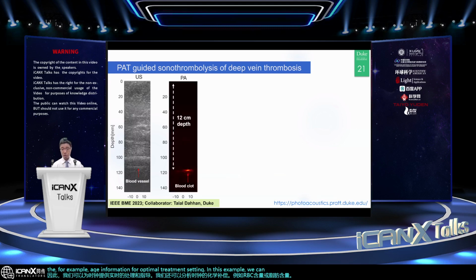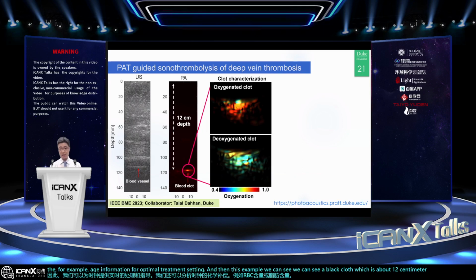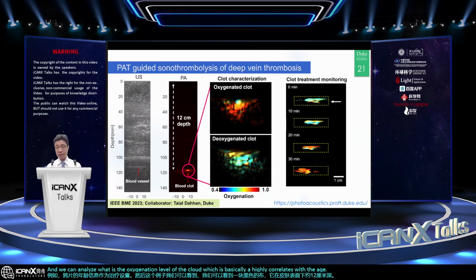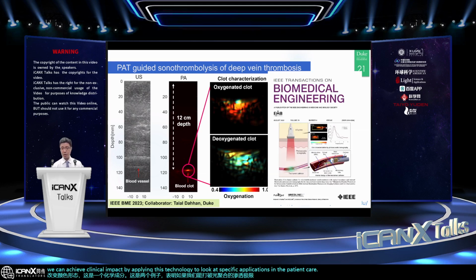In this example, we can see a blood clot, which is about 12 centimeters deep underneath the skin surface, and we can analyze what the oxygenation level of the clot is, which highly correlates with the age of the clot. And we can also look at how the treatment changes the clot morphology and its chemical composition. So these are 2 examples showing that if we can break the penetration limit of photoacoustic imaging, we can achieve clinical impact by applying this technology to specific applications in patient care. This work has recently been highlighted by IEEE BME.